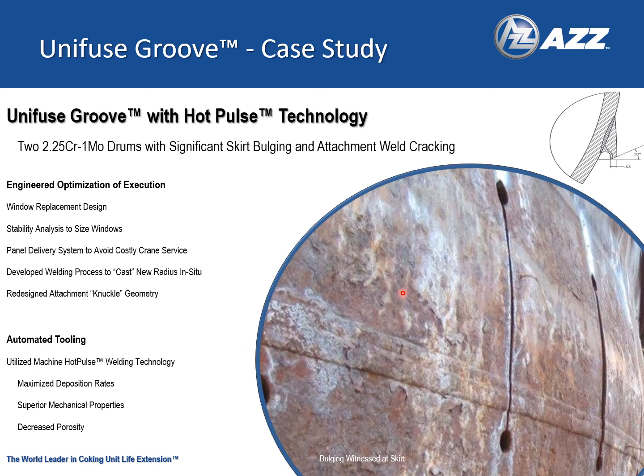This customer was experiencing significant bulging of the upper skirt and cracking at the skirt-to-vessel attachment. The vessel is 2¼ chrome 1 moly construction. The original vessel design had an improperly designed knuckle region that caused early cracking at the skirt-to-vessel attachment. AZZ developed an engineered repair solution that involved the upper skirt replacement in sections and a complete removal and reconstruction of the knuckle area. In this sketch, we can see the knuckle section that was replaced and reconstructed with weld deposit. For a proper design, it was necessary to reestablish an ample radius at the knuckle to vessel connection.